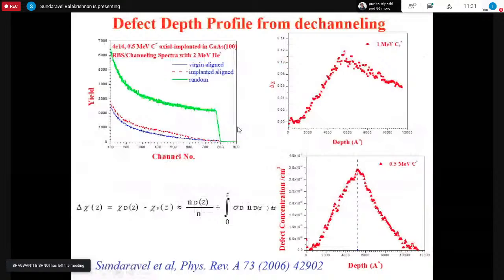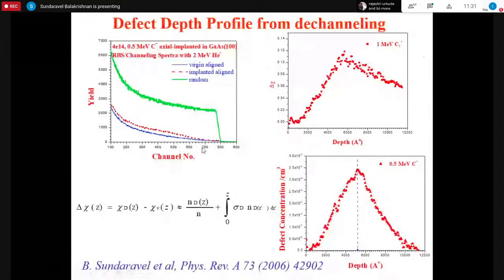And as such, I told that we can find the defect concentration as a function of depth. For that, say this is the RBS spectra from random, while the lower ones are from channeling spectra from virgin and implanted samples. If we divide the random with the channeled, we get chi, and the difference of chi between aligned and random is plotted here as a function of depth. We extract this, and then we have delta chi at various depths. This delta chi is given by this expression. Nd is the defect density, n is the total atomic density, this one is the dechanneling cross section, and dz is something like 20 angstroms.